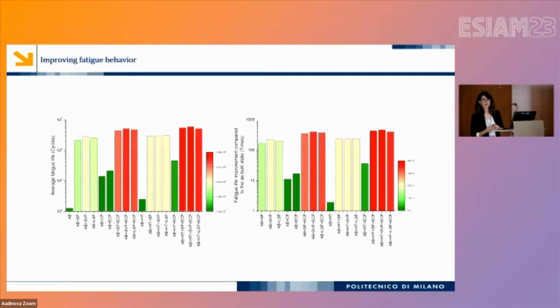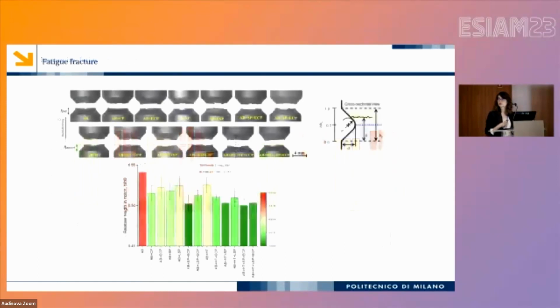We are getting the best results because we are getting all the benefits from the residual stresses and the surface parameters, hardness, that is changed. But we are also removing the top surface layer, which has the highest surface roughness. So we are reducing also the surface roughness in that area.